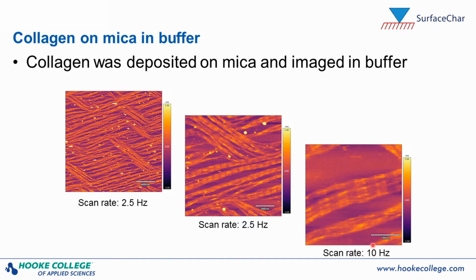And you can see it was actually scanned pretty quickly in fluid at 10 hertz. Typical scan rate for AFM images is on the order of 1 to 2 hertz. So this is pretty fast, especially for a large sample instrument, and getting really crisp, clean resolution in fluid.